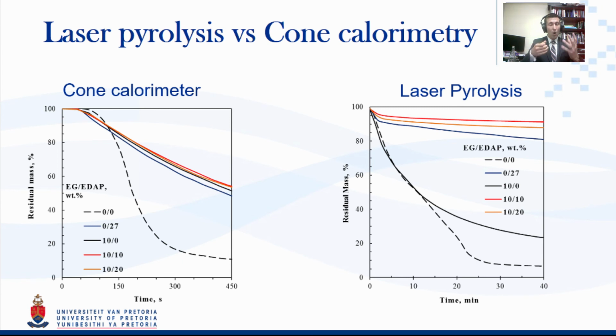We found that on our small scale laser pyrolysis, we actually found a lot worse performance for the 10% expandable graphite material. And we believe that this is closely linked to its thermal behavior that we tried to address, in that it did not create a cohesive barrier, and that the laser energy that was transferred caused a very quick burn through of the strings as they came out, because they were not bonding to one another to block the thermal event. But outside of that, all of the trends are similar.